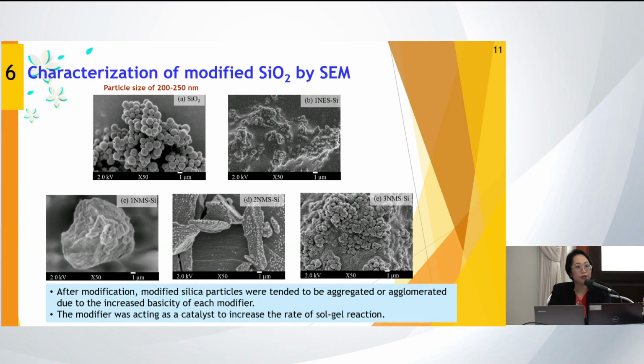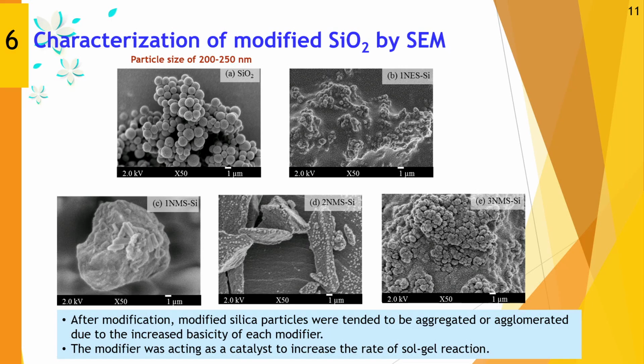Here I would like to show you the morphology of the modified silica particles using scanning electron microscopy. You can see that the silica particles before modification show a spherical shape with a particle size in the range of 200 to 250 nanometers. And after modification, the modified silica particles tend to be aggregated or agglomerated due to the increased basicity of the modifier. It is because the modifier can act as a catalyst to increase the rate of the sol-gel reaction.